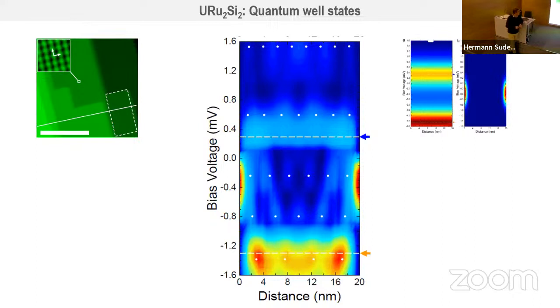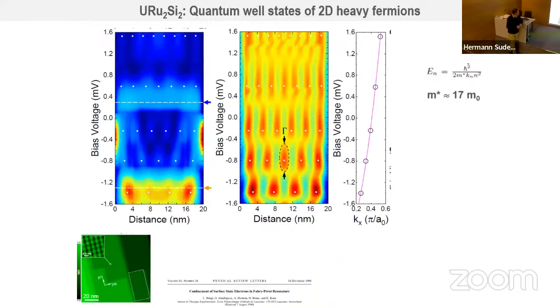So this is an edge state. I will go to this later. And these are probably changes in the band structure in the bulk. So once you remove them, then you can make a comparison with a Fabry-Perot analysis. And you can see that you have this quantization, which works nicely as a function of the energy.